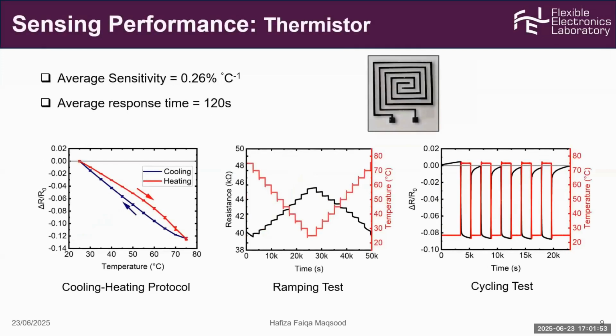For the characterization of the thermistor, we followed the cooling heating protocol instead of the heating cooling protocol in order to ensure the reliability of our sensor. So here a non-linear trend is reported, which is attributed to the IGZO due to its negative temperature coefficient of resistance, and negligible hysteresis was observed, which is likely due to the polymeric nature of the substrate.